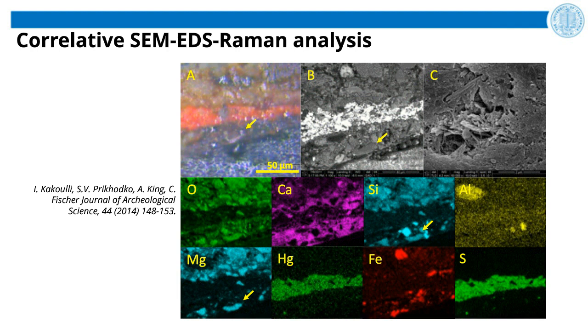and by the way, we can clearly see that on the optical image, it is very hard or practically impossible to see this individual inclusion, whereas on image B, this inclusion can be seen quite well. And the high magnification, high resolution image shows the fibrous morphology of the inclusion, which also suggests that it might be asbestos. However, even with such strong evidence, it was kind of brave for us to suggest asbestos, since the use of asbestos in the manufacture of cements and plaster was thought to be a novelty of the late 19th century, and we're dealing with an artifact from the 12th century.